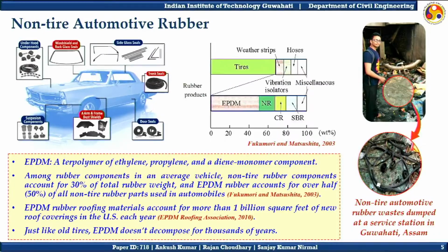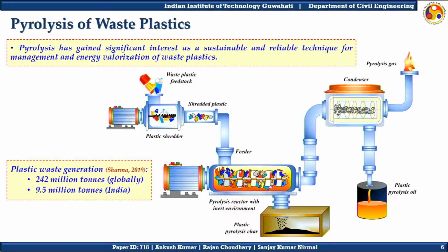So we tried to explore alternative source of its application as asphalt binder modifier. So coming to the second component of the modifier, that is plastic pyrolysis oil. As we all know, plastic waste has been a menace for India and globally. So pyrolysis has gained significant interest as a sustainable and reliable technique for management and energy valorization of plastic waste. So in this pyrolysis process, we collect the plastic waste, we clean it, and then we shred it in smaller sizes and feed it in a pyrolysis reactor for thermomechanical and chemical decomposition at very high temperature to generate vapors.